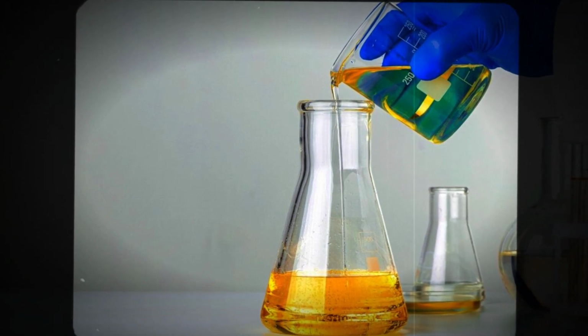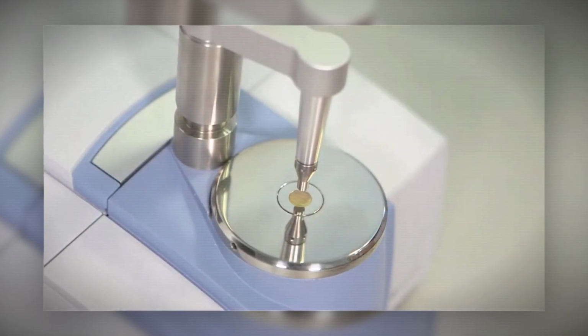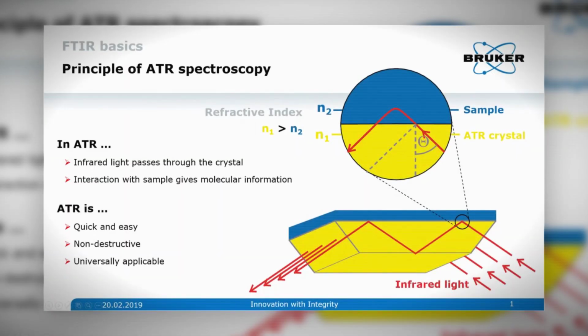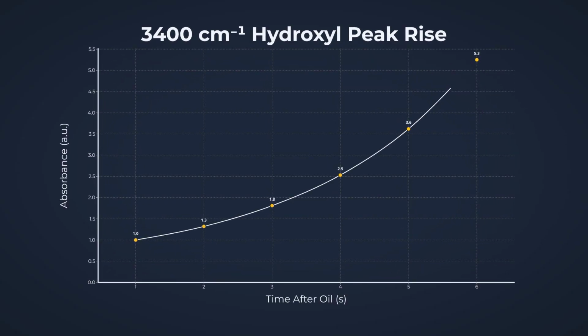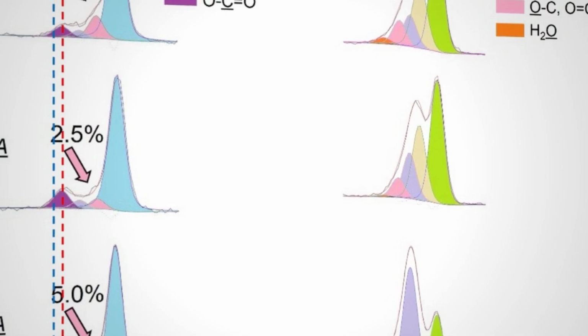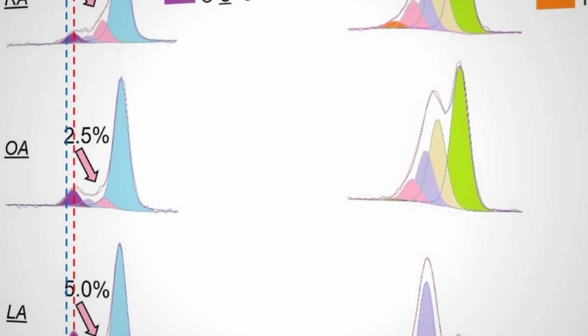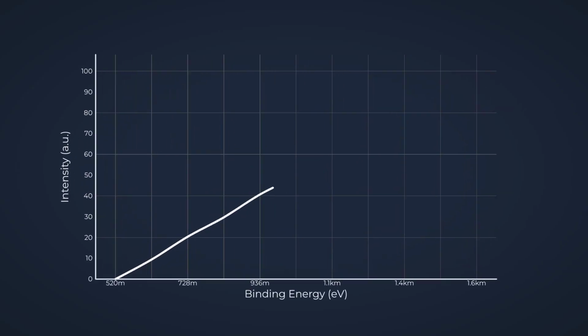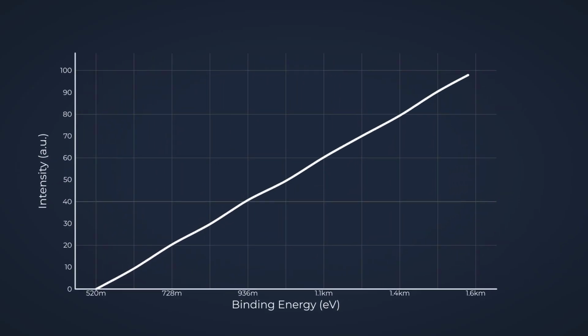through aggressive additive chemistry. FTIR spectroscopy confirms the presence of the hydroxyl band at 3,400 per centimeter on iron oxide surfaces, direct evidence that ricinoleic acid chemically bonds to the metal. X-ray photoelectron spectroscopy picks up the O1s peak, further confirming chemisorption. The engineering result is a boundary film that resists being stripped away under high pressure and high temperature.